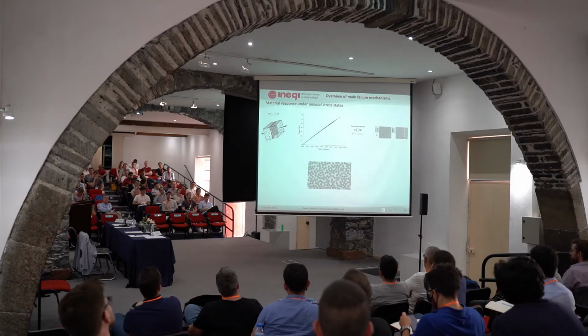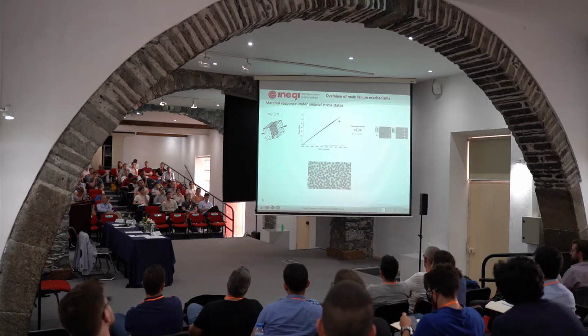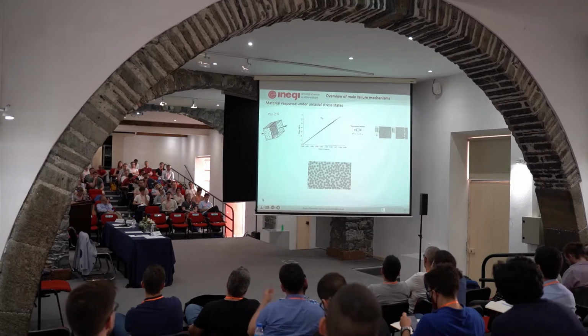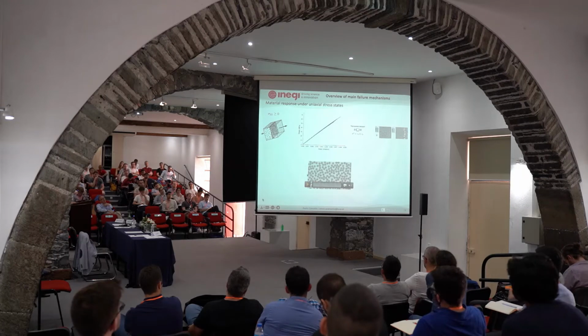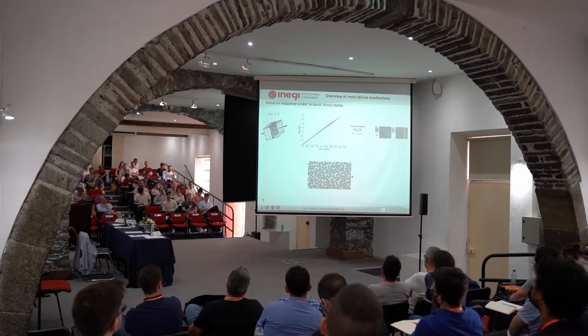Okay, so let's move now to transverse tension. Again, you have a linear elastic response. You have a brittle failure, but at low stress, and this is what you get. You are applying transverse tension, so you are loading in this direction in tension. Again, this is a computational micromechanical model. You get a crack that is, in a global sense, perpendicular to the loading direction, as you can see there. So not very complicated in this case.